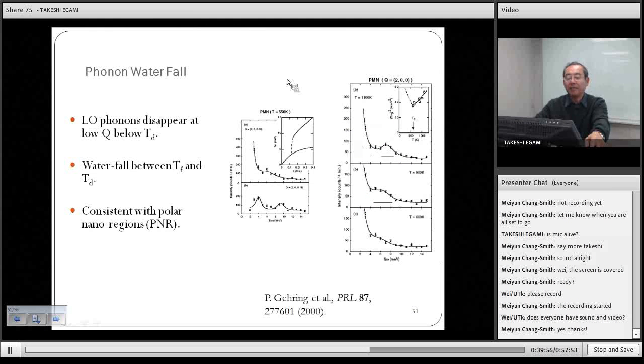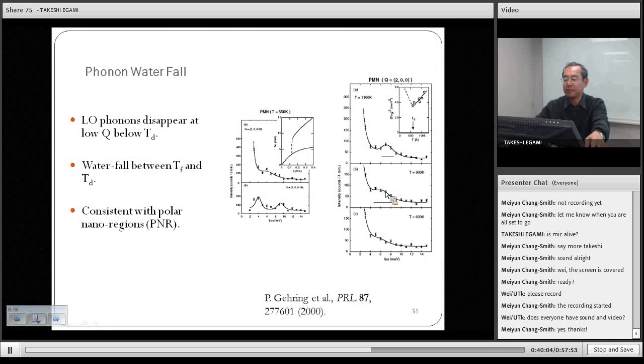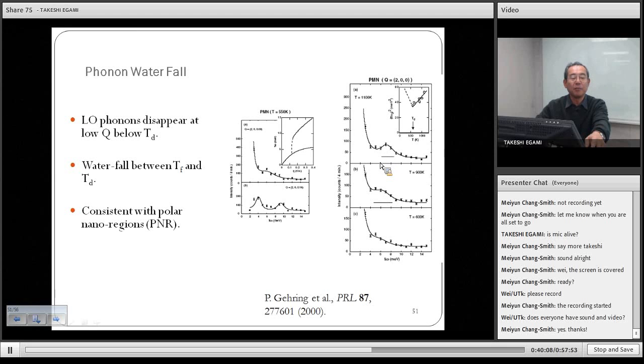behavior. For instance, if you look at phonons, you can observe phonons. These are the phonons by neutron scattering. And as you can see, compared to the regular crystalline case, phonons are very broad, right? Very broad. In crystalline materials, it's much sharper, but this is very broad. And this is because of this strong disorder. Not only that, below a certain wave number, it just disappears. The phonon disappears, okay? This phonon usually should be like that, but it simply disappears. It may or may not go down, so it's sometimes called a waterfall. But essentially, this phonon disappears.